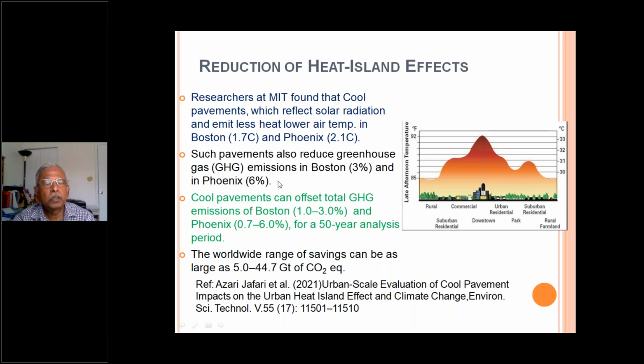And they also found that cool pavements can offset total greenhouse gas emissions of Boston by 1 to 3%, and in Phoenix by 0.7 to 6%, for a 50-year analysis period. The worldwide range of savings can be as large as 5 to 44.7 gigatons of CO2 equivalent. Of course, I have given some references in these slides, so you can go through them for more details about what I am discussing.